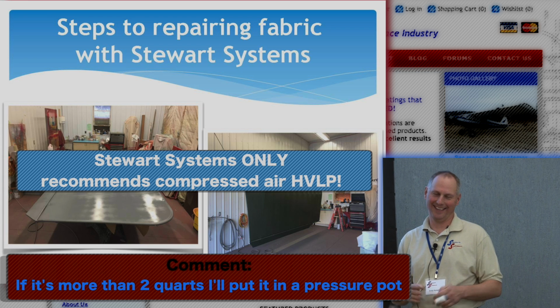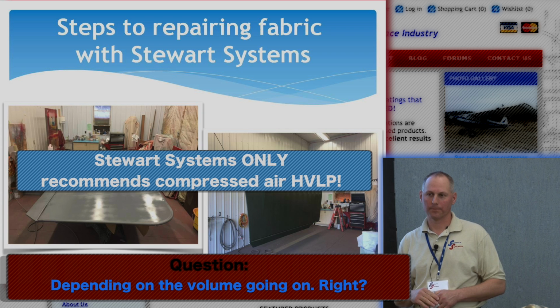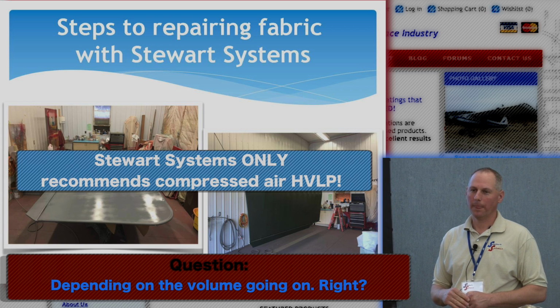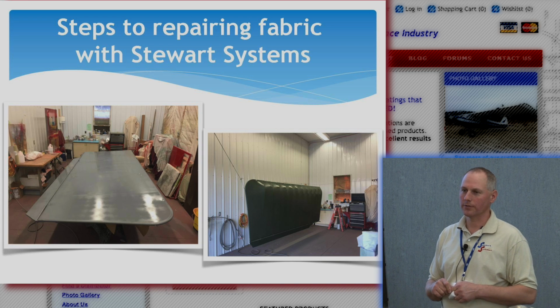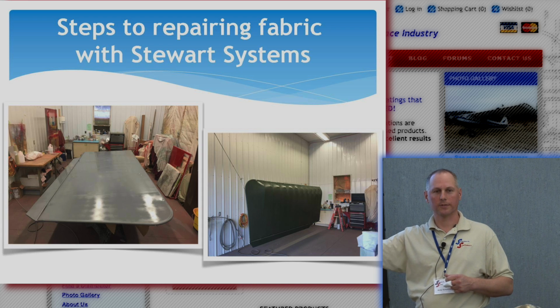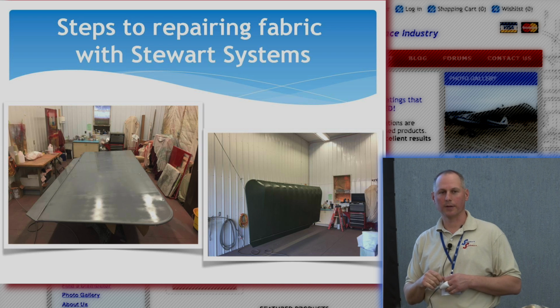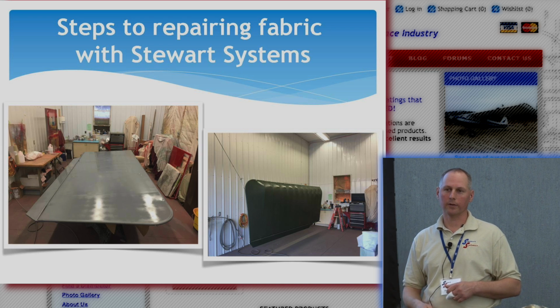Okay, well, give it a try. It may work fine, depending on the volume you want on. We're not putting a huge volume on, so the key with our paint is getting it atomized really well. The technique we're using is a real light tack coat, then a few fog coats, a little bit heavier, but we don't want the paint to flow. It should look like 1,000 grit sandpaper. We build that up with about 3 fog coats, then put a wet coat on, and we're done.